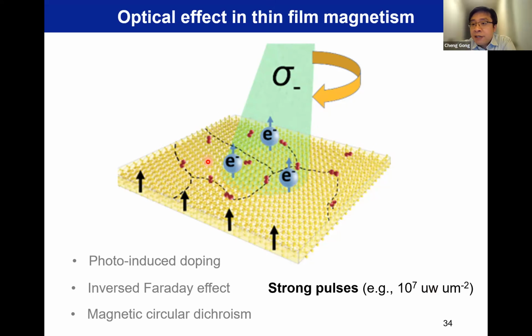Basically, you have materials with a spin-up domain and a spin-down domain. When you shine circularly polarized light, one spin-polarized domain will absorb the light more than the other spin polarization. So that will be heated up just above TC. The other one, absorbing less light, will not be heated up to be demagnetized. So the heated-up one becomes demagnetized, and given this is ultra-fast laser pulses, between pulses you have a long window, and it will cool down. And when you cool down, you have a 50-50% chance to go to either the original spin or flipped. But laser pulses keep being incident on this sample, and finally your sample is flipped.